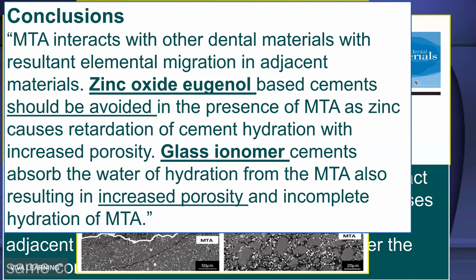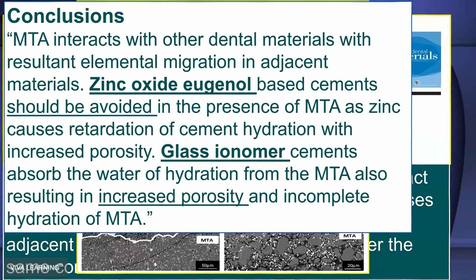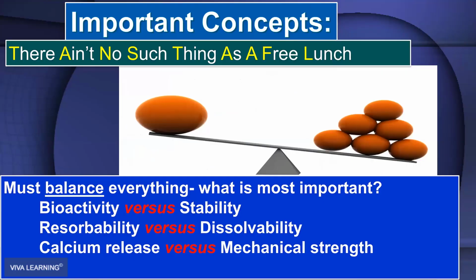MTA reacts to a lot of materials, such as zinc oxide eugenol, like IRM materials, and they should be avoided in the presence of MTA. Zinc causes retardation of cement hydration with increased porosity, and glass ionomer cements absorb the water of hydration from the MTA, also resulting in increased porosity and incomplete hydration of the MTA. And that's something you don't want, because then the MTA has to keep trying to pull fluid out of the pulp itself. Well, there ain't no such thing as a free lunch. We all know that. So you have to balance everything: the bioactivity versus the stability, resorbability versus dissolvability, and calcium release versus mechanical strength.